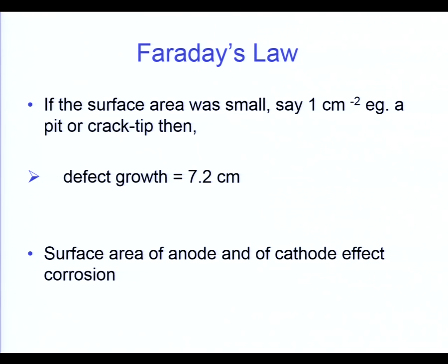And there's an interest in the ratio of the anode to cathode process. Remember, the two processes occur at equal and opposite rates. One of them is generating electrons, the other is using up electrons, and they have to balance. So if you've got a cathode of a particular area, then only so much oxygen reduction or hydrogen reduction can occur on there. There are limits because of the area of the electrode in contact with the solution and the diffusion of the species to and from it.